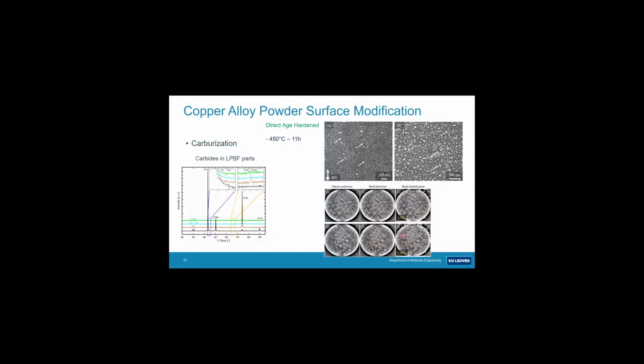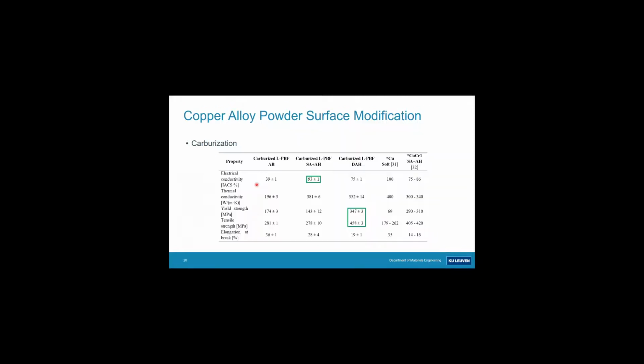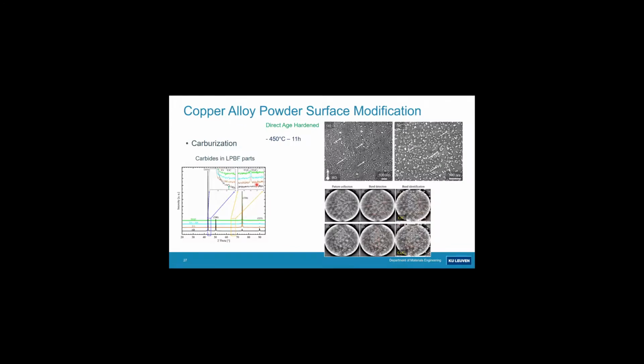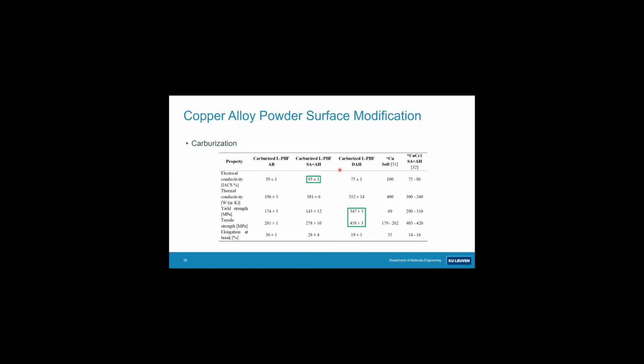And we found 2 types of carbides, so either chromium 1 carbon 1 or chromium 3 carbon 2 carbides. So you could still find these carbides in the laser powder bed fusion processed parts, which means that at least part of the carbon remained there as carbides. They reacted to heat treatments, and so what we often compared is a conventional solutionizing plus age-hardening heat treatment with a direct age-hardening treatment because of the very high cooling rates during laser powder bed fusion. You supersaturate your matrix, and there is a fair chance that this is probably more efficient than a separate solutionizing heat treatment. And you have actually more control of the size of the precipitates you form there.